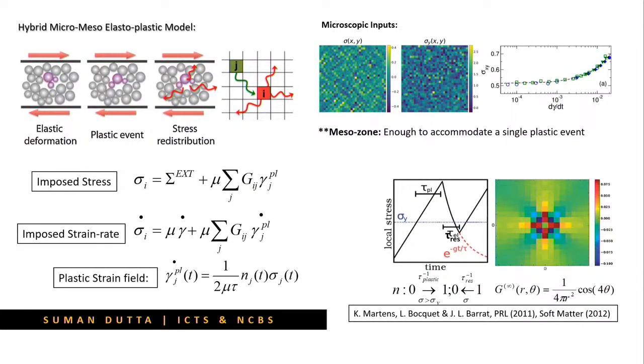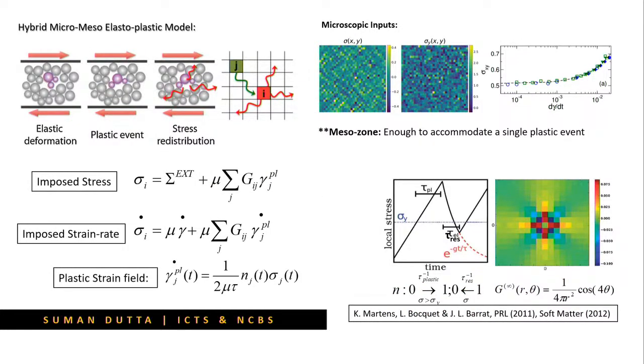So, for this we tested an elastoplastic model. This is a lattice-based model, which has some similarity with the earthquake model by Bak, Chen and Tang. We have this lattice, and at every point we have variables like the stresses, and the stress and its change depend on three different things. One is the elastic deformation, then we assume that plastic events are happening, and then how these plastic events are correlated. We use a propagator to correlate these events, and then there is a stress redistribution that happens due to the plastic events.